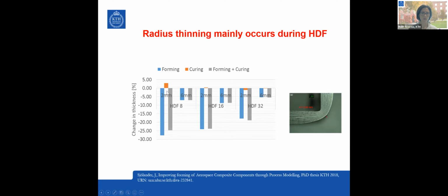During curing, you also had a small change in thickness, but it was not at all as large as you had during forming. And the total afterwards was often quite close to the thinning that we got during forming. So with that said, we do not need to put a lot of effort into the bagging during curing, because you always have to do that. That was a bad way of saying it. The focus here is to understand that the thinning has already happened during forming. So if it happens during forming, we also need to understand how we can avoid it.